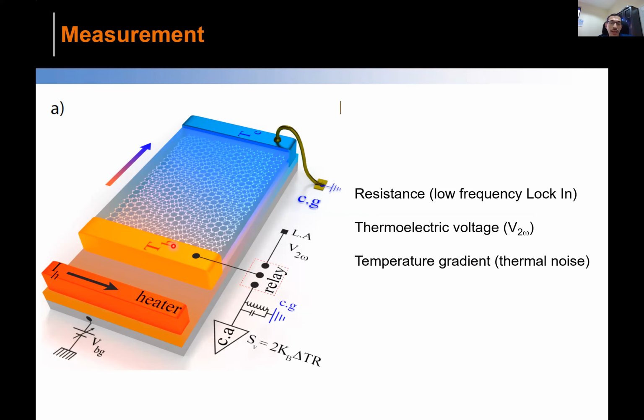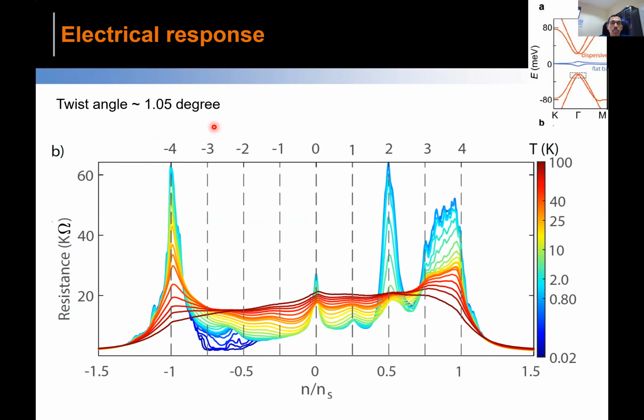And this is the technique I was telling you about: our lab has been in this thermal transport business. We measure the thermal noise, which is proportional to the temperature. So by measuring this thermal noise, we can accurately measure this temperature difference. In fact, with our technique, we can measure less than a millikelvin temperature difference between these two contacts. Okay, so these are the two important things.